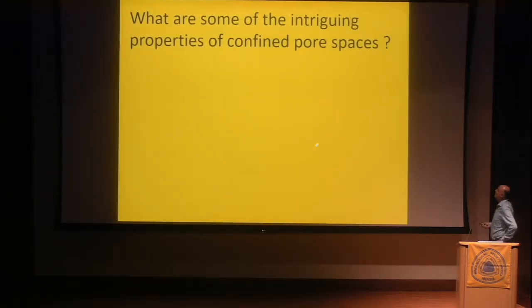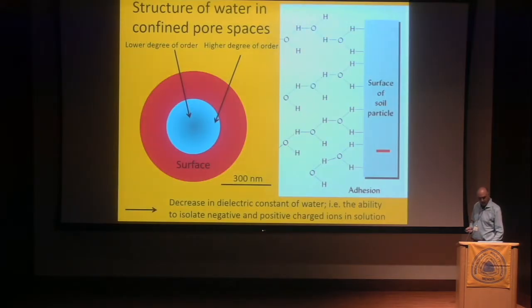So what are some of the intriguing properties of confined pore spaces? When we take a mineral surface, we have here the surface atoms, and we have here the adhesion forces between water molecules and the surface atoms. And as we know, we have highly ordered water molecules along the surface, and this ordering effect goes out, and we have less ordered water when we come to a further distance from the surface. So when we have here a pore space with, let's say, a diameter of 300 nanometer, we obviously observe a higher ordering degree of water in the outer part of the pore space, and in the interior, which is further away from the surface, we have a lower degree of ordering.